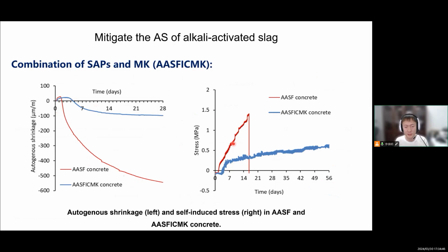And then the cracking potential is also reduced a lot. So if we do not apply this method, it's cracked within 3 weeks, as we already mentioned. But if we apply this tool, the cracking didn't happen in 3 months. The stress is lower than 0.5, so it will never crack, I think.